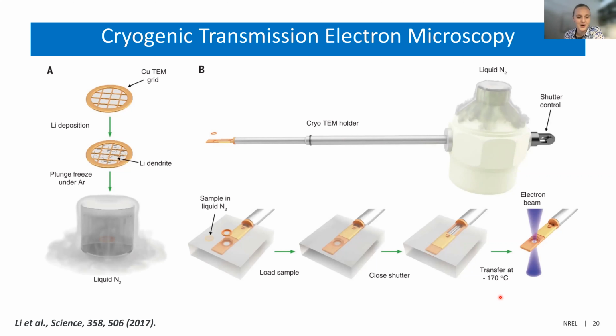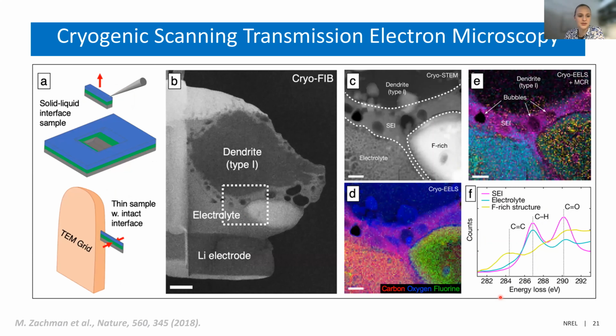The other paper that was very inspiring to our group was this one from Lena Kourkoutis and Michael Zachman from Cornell, where they were able to set up a focused ion beam where they had a cryo stage to hold the sample, and then they also had a cryo lift out needle so that the sample stayed cool so that they could lift out an electrode in contact with an electrolyte. And so you're seeing here a lithium dendrite in contact with an electrolyte, and then they could image this inside the STEM with EELS to then get maps of the carbon, oxygen, fluorine peaks to better understand the SEI in contact with the lithium and the types of lithium dendrites that would form after electroplating.